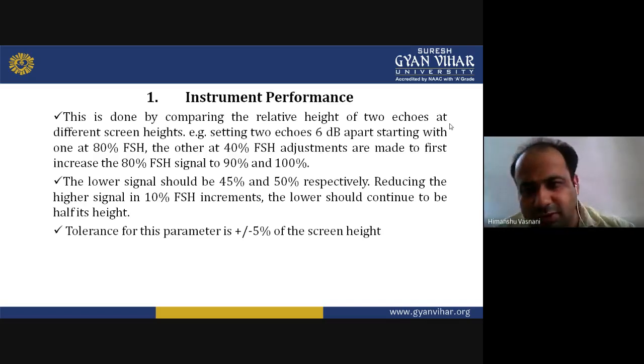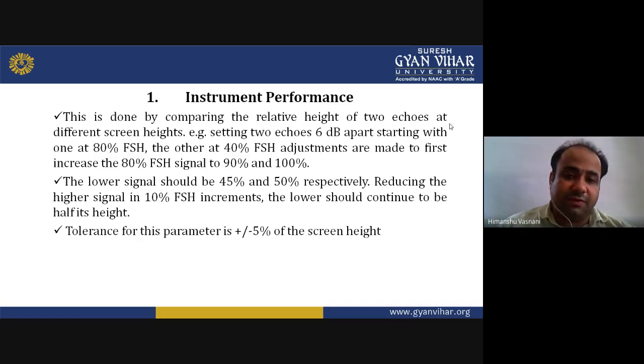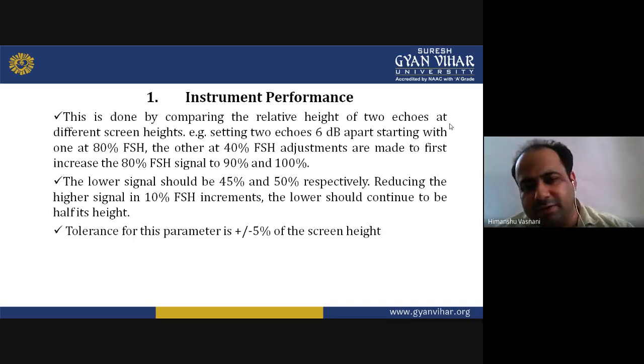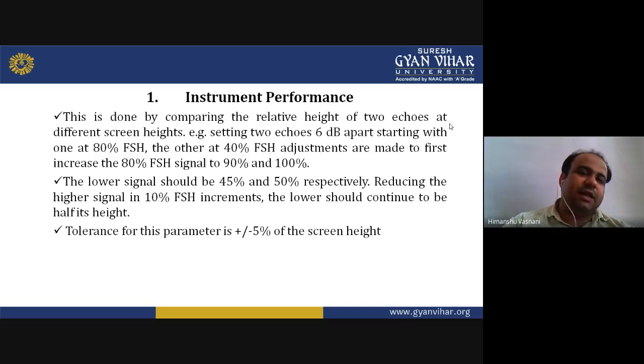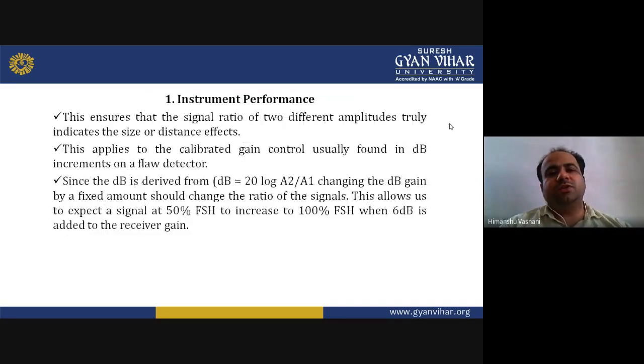For example, getting two echoes 6 decibels apart, starting with the first at 80% FSH and the other at 40% FSH, adjustments are made to the first: increase the 80% FSH signal to 90% and 100%. So the lower signal should be 45% and 50% respectively, reducing the higher signal in 10% FSH increments. The lower should continue to be half of it. In this way, they maintain the performance. The tolerance for this parameter is plus or minus 5% of the screen height that we have just seen. This ensures the signal ratio of two different amplitudes truly indicates the size or distance effects.